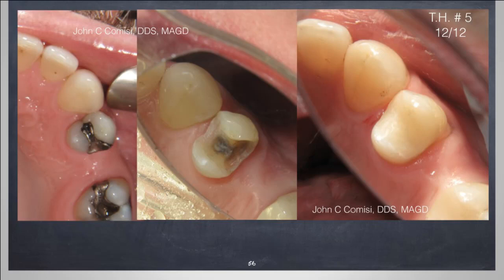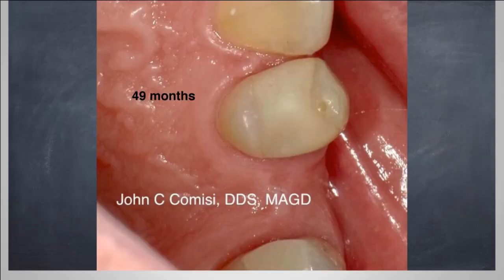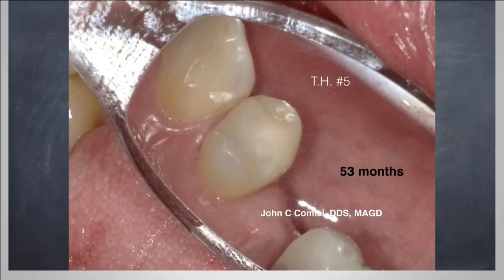We then did some follow-ups, and after 49 months, the restoration was holding up spectacularly at that point in time. Even at 53 months, we still have a really nice result. There's no breakdown, there's no marginal leakage. The tooth is in function all the time against the opposing teeth. And again, it's holding up well.